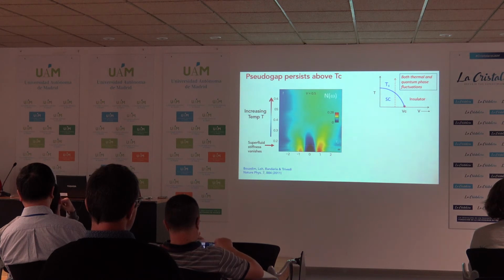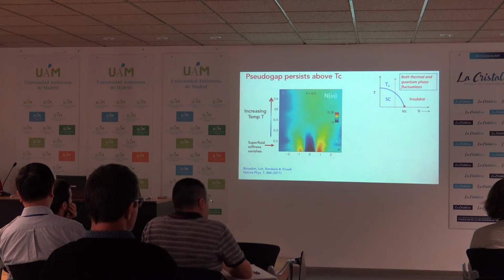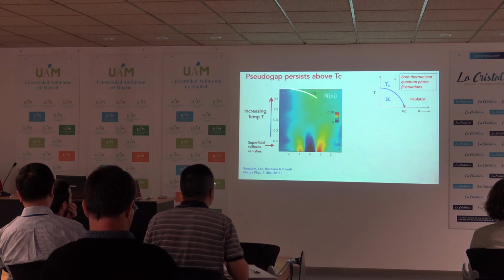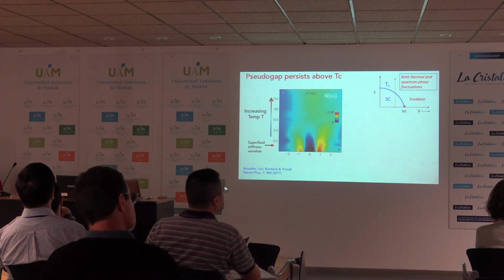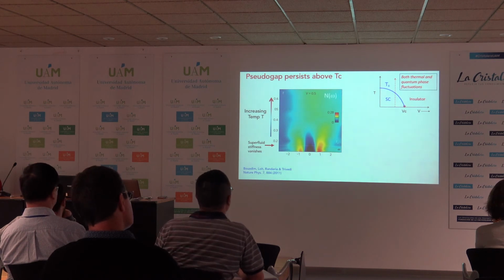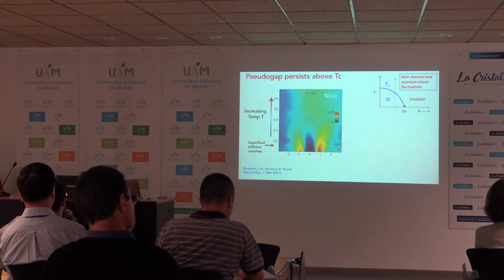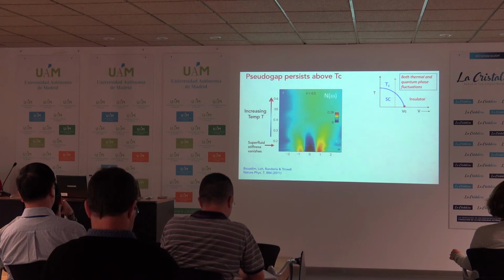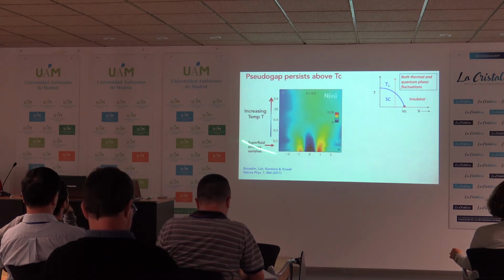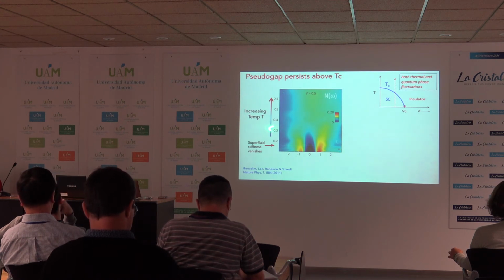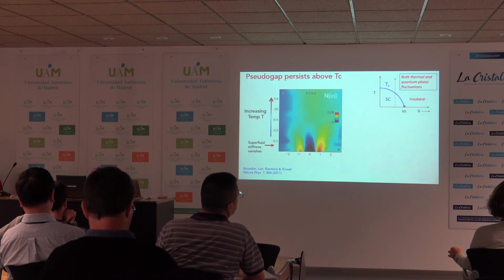So the importance of some of these results in view of the cuprate story is, even though the actual microscopics is very different, that's a repulsive problem, and magnetism is important. Here we have, without worrying about the origin of the superconductivity, some attraction, but it is important to see the phenomenology that emerges. And here we see that in a nominally BCS superconductor, by adding disorder, we can get this kind of a pseudogap. In this case, it is entirely due to pairing. So pseudogaps can have many origins, could be what we heard earlier, but here it is entirely due to pairing. Or in other words, these patches remain, and it's the phase fluctuations that become soft at Tc. So even above, in the normal state, you still have pairing on these patches.